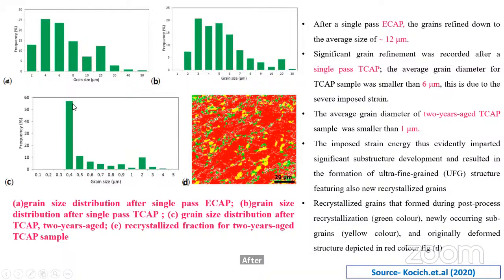You can see the frequency percentage versus grain size. This first diagram is the grain size distribution after a single pass ECAP. The second diagram is the grain size distribution of a single pass TCAP process. You can see the grain size distribution after TCAP and 2 years aging. In the 2 years aged sample, the grain size goes on decreasing, and it is very, very fine after 2 years aging.